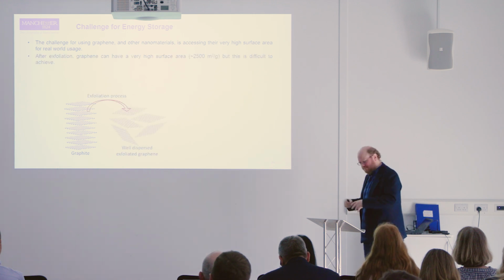One of the biggest challenges for energy storage is, graphene seems like an ideal material. It's got high surface area, it's highly electrically conductive. Why is it not everywhere? One of the problems is, particularly for top-down production methods, if we take graphite, we exfoliate it, we produce a nice dispersion or a powder or whatever form it may be, we've got this really, really nice high surface area material. And now I want to integrate that into my battery coating line or my supercapacitor, which means I make an electrode out of it and it restacks. So I lose all of that really nice high surface area that I wanted. So I'm lucky if I get maybe a few hundred square meters per gram, which is nowhere near the 2,500 square meters per gram I was promised. So there's really a big problem here.